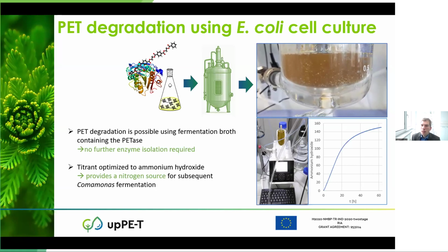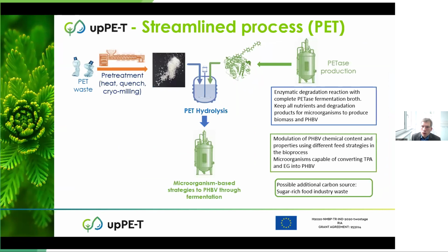In order to further optimize our material, which we provide for the fermentation of Comamonas in the end, we also optimized the titrant, which is used to neutralize acid, which is released during the cleavage of polyethylene terephthalate. And we came up with ammonium hydroxide as an alternative titrant. This has the advantage that it also provides a nitrogen source for the subsequent Comamonas fermentation. So with all of our optimizations, we streamlined the PET degradation process, thus using the pre-treated PET waste and the enzyme which comes directly from a fermentation broth for the PET hydrolysis.